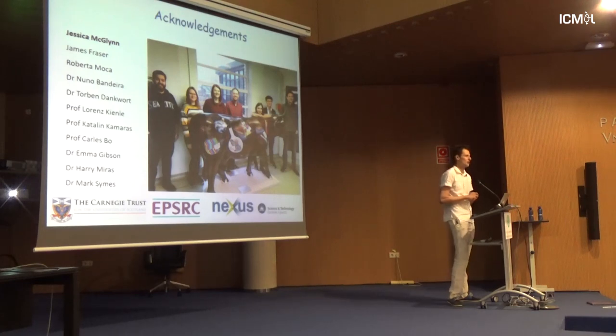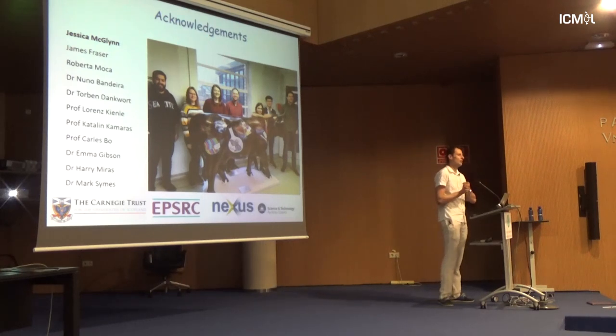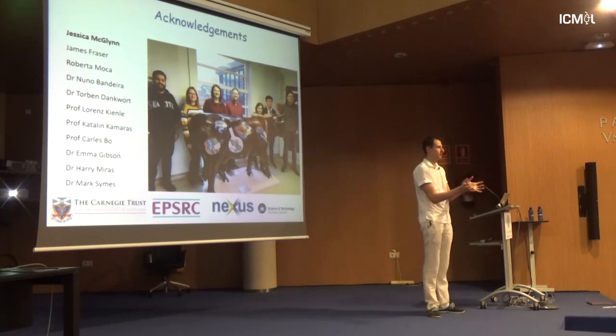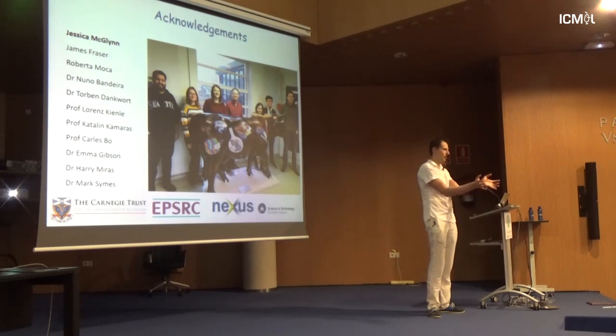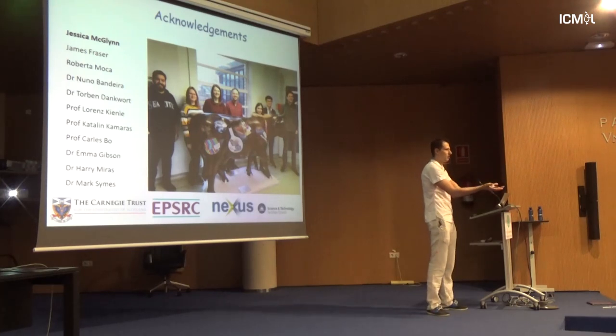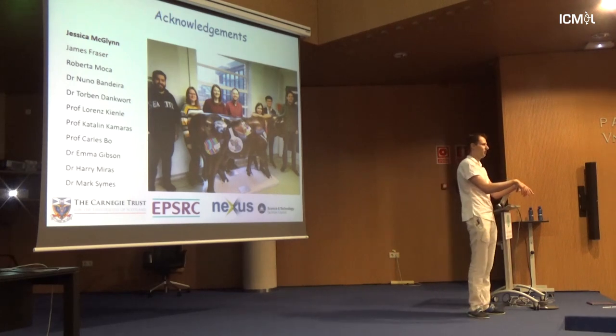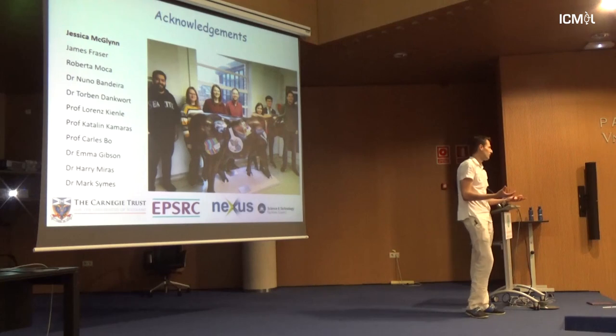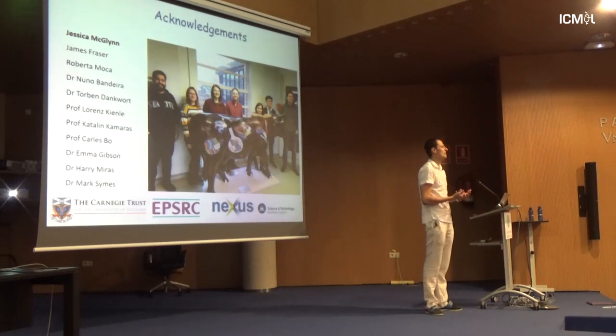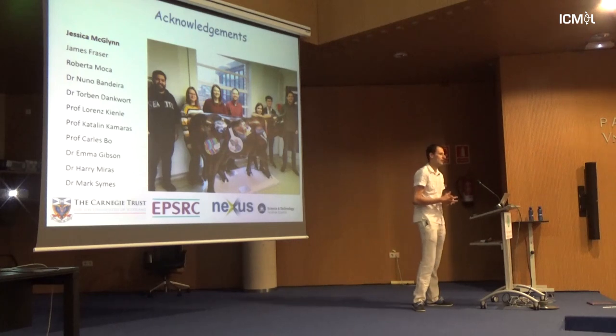We have samples of molybdenum telluride, but still didn't manage to check them. It's the question of how you attach them to electrodes, so we're tinkering with it. We can grow large films of molybdenum telluride on silicon oxide. But you can't measure on silicon oxide, so you need to take the entire film and transfer it onto some substrate. We're trying with gold, but the problem is you stick it into your acid and it just falls off. So it's a question of design, and it hasn't come yet. It's a good design, and that's the goal. So we will see how it works on exfoliated material. Yes. Thanks.